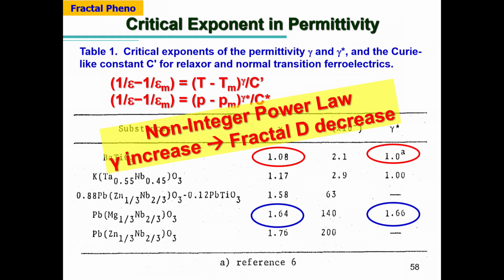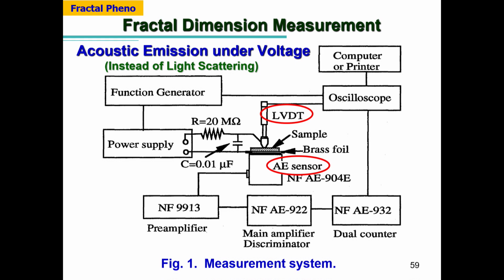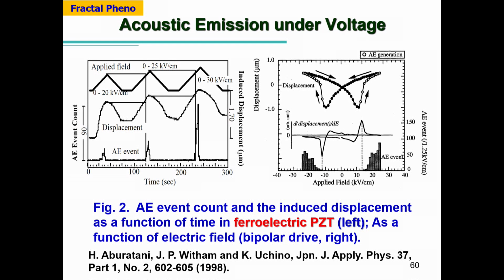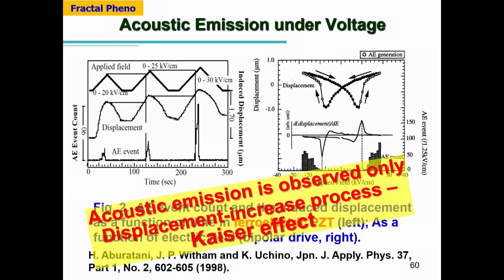This is expected. So how to measure the fractal dimension macroscopically? Instead of light scattering, we started to use acoustic emission. Of course, my former company is NF Corporation, that is an AE sensor company. We had sophisticated AE sensors. So even when deformation happens, we can measure the acoustic emission. Under voltage, basically, acoustic emission can be observed only when the displacement increases. When it decreases, no acoustic emission. And then again, increase.